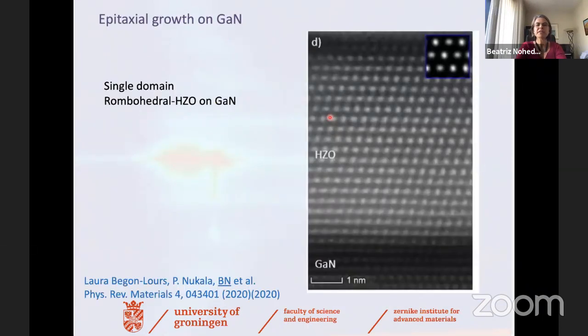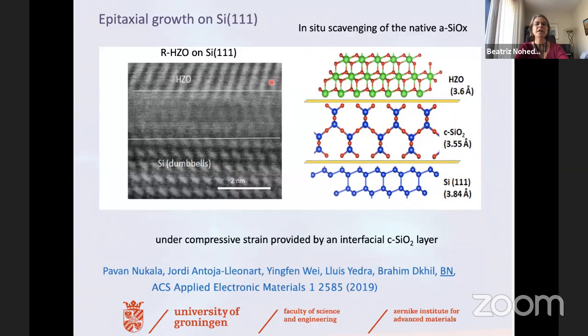So this rhombohedral phase happens to be not so strange and not so rare. We could also grow that in collaboration with the group in Twente, with Hans Hilgenkamp and Gertjan Koster, on gallium nitride. And on gallium nitride, we could actually grow single phase rhombohedral films that can be imaged very nicely by electron microscopy and confirm that this phase is indeed not orthorhombic, but a rhombohedral phase. And it can also be grown nicely on silicon 111.